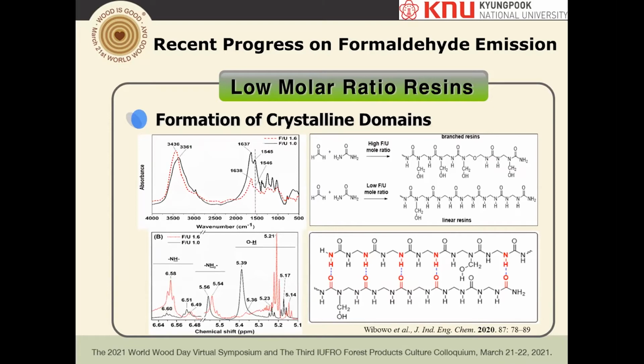And then we look at what was happening in here, and then we look at the FTIR and the proton NMR. And what we found is this is NH and this is the carbonyl groups. Comparing, the red dotted line is 1.6 and the black solid line is the 1.0 line. So there are some different shifts of these wave numbers. That means the NH is moving because of hydrogen bonding between linear molecules in the low molar ratios. It's the same thing in the carbonyl groups, and also the same thing in the proton NMR. So the chemical shifts are moving up here and over here as well. So this means this resin has a hydrogen bond.